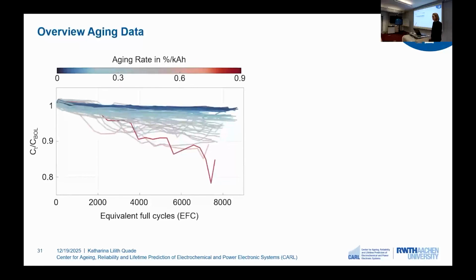So now I want to introduce the results of the aging study. On the x-axis, you can see the equivalent full cycles, and on the y-axis, you can see the normalized capacity. The color corresponds to the aging rate, that is the ratio of the capacity loss to the charge throughput. And we can see that the aging tests are well advanced, with some cells having reached more than 8,000 equivalent full cycles. And that is quite remarkable, and such data has not been reported in the literature for sodium-ion batteries yet. And even for graphitic lithium-ion batteries, such a lifetime is very high.